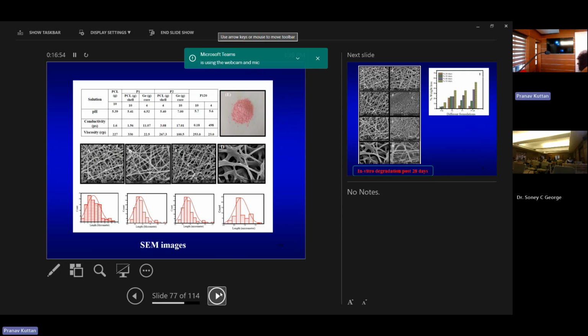So this is the condition we have chosen: PCL alone we did the electrospinning, then using different combinations, P1, this is 10, and 4 different ratios we have chosen. Conductivity and viscosity are all parameters which we generally measure before electrospinning. And this is the GSNO, that is the nitric oxide complex, which is required for antibacterial property. And these are all the SEM images showing different sizes, like this contains nitric oxide. So all these membranes were chosen.